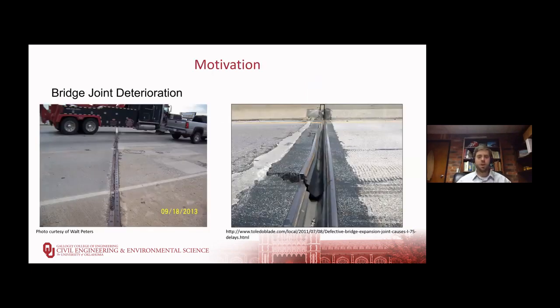So the motivation for the work that we've been doing at OU originally came out of a lot of problems that we were seeing with bridge joints throughout Oklahoma. We have a lot of deteriorated bridge joints in Oklahoma, and you can see an example here on the left of a bridge joint where we're losing some of the steel armoring. The joint has started to close up. We can see some spalling of the concrete around the joint. And then on the right side, we can see that the bridge deck slabs have offset, creating a bump there in the road. Our joint sealant material is coming apart, which is going to allow water to get down onto our bridge structure.